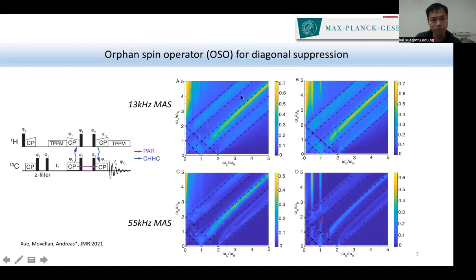Since the MAS is very slow, with a ramp we easily also cover the power condition during the CP time. This is actually not a problem for faster spinning because our MAS is fast. Then the power that we set on protons is, let's say, 50 kilohertz or 100 kilohertz. So even with the ramp, this arrow region is still very narrow and doesn't touch the power conditions. Meaning that our valid signal pathway here is not the same as what I introduced previously.